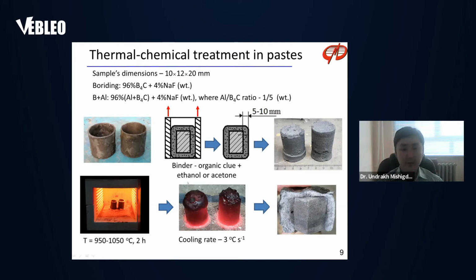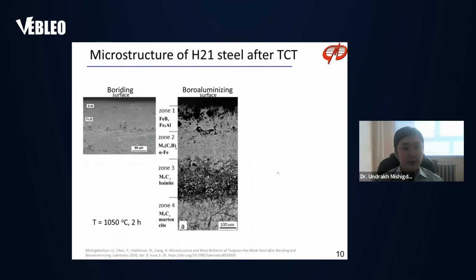And the dried briquettes were placed in a furnace preheated to the treatment temperature for 2 hours. After exposure, the samples were removed from the furnace and cooled down to ambient temperature. After that, the samples can be easily separated from the dried paste. As a result of treatment, different microstructures were obtained.